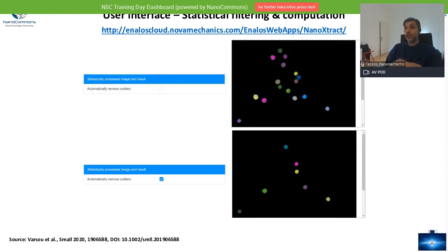so you can perform the calculations. But my advice and experience says that if you get to a point like this, where you see that more or less all these nanomaterials look the same and are in an acceptable range, then you should not use statistical filtering, because then you will lose statistical significance in terms of your replicates, which is going to be based on one single nanodescriptor, and keep only very few particles that actually fit all the ticks statistically.